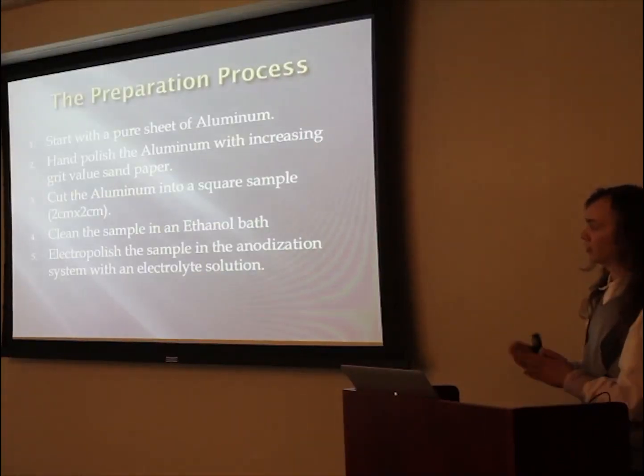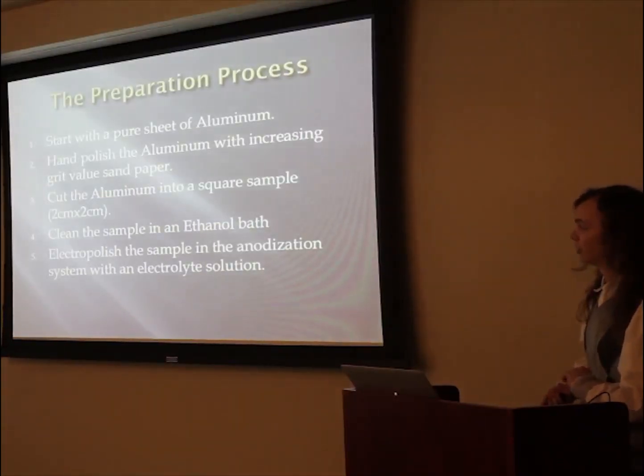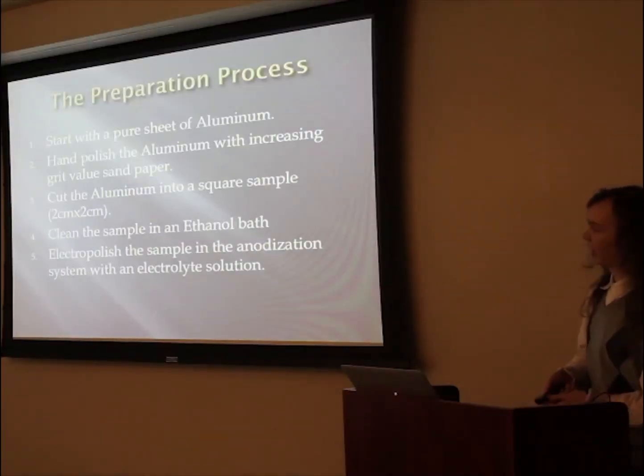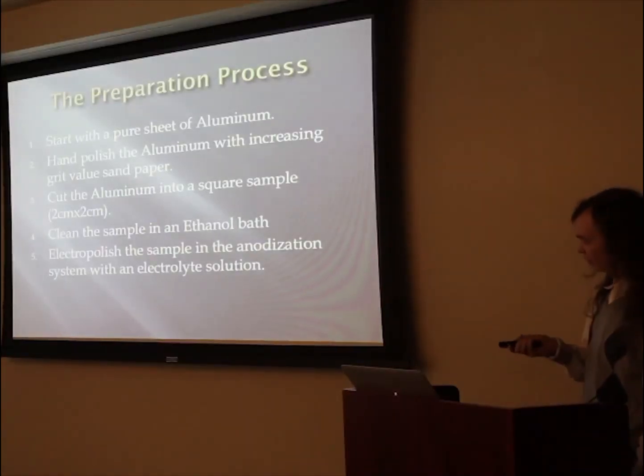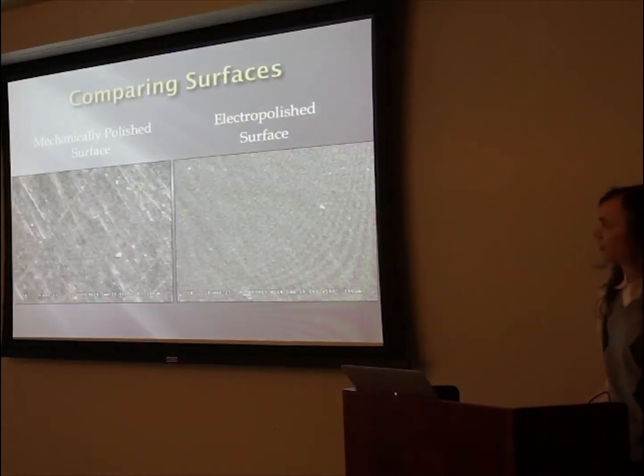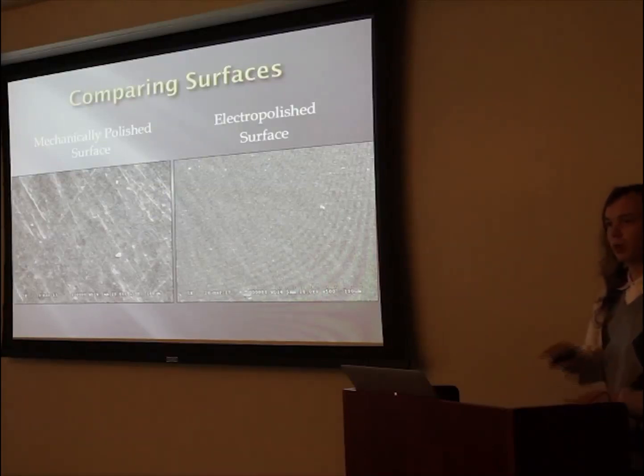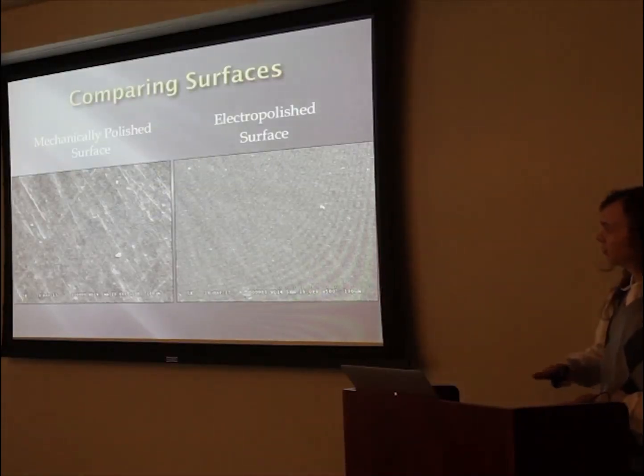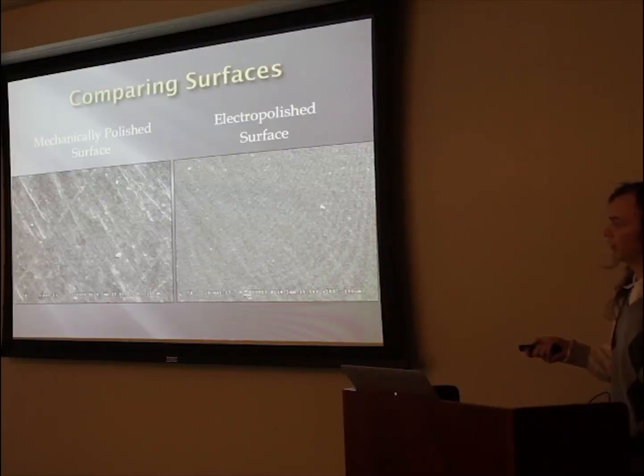Then after that, you cut it into a small sample. We use about 2 by 2 centimeters, clean it in a bath, and then you can electropolish it after that. So the reason we want to do this is from first buffing it out with a mechanical polish, you get a lot of grit lines on it. So you push down a lot of the bumps to the surface, but you end up getting these scratches alongside of it. And we don't want that.